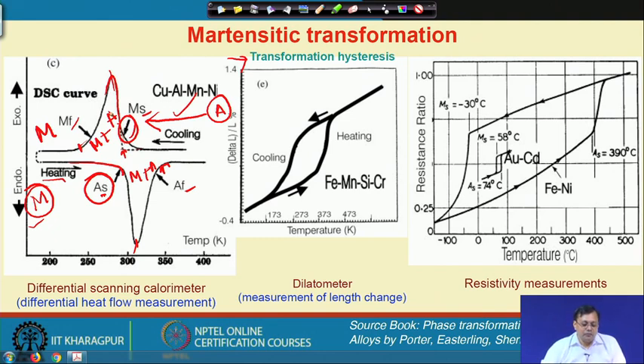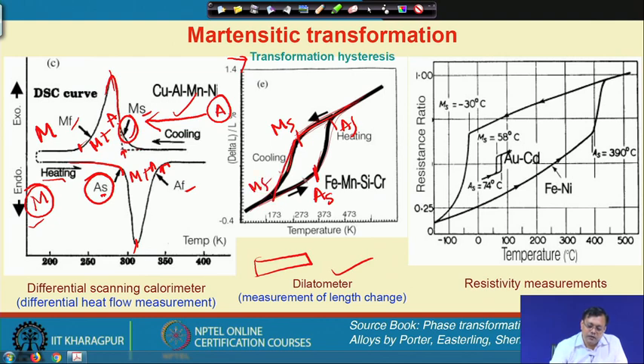A very similar feature people have observed in the case of a dilatometer. In a dilatometer, the length changes or dimensional changes are measured. So, if you take a small rod of such a martensite, then in a very similar way you will see this kind of hysteresis, where here is the austenite start, here is the austenite finish, and here is the martensite start, because the slope changes. Here is a plot which is linear and then the slope changes, so the transformation has begun here. Here the slope also changes, that is why the transformation begins here. So, this is actually MF. And between the martensite finish and austenite start, there is always some sort of lag, you can see. However, these temperatures are somewhat closer, because the transformation requires some extra energy and so on.